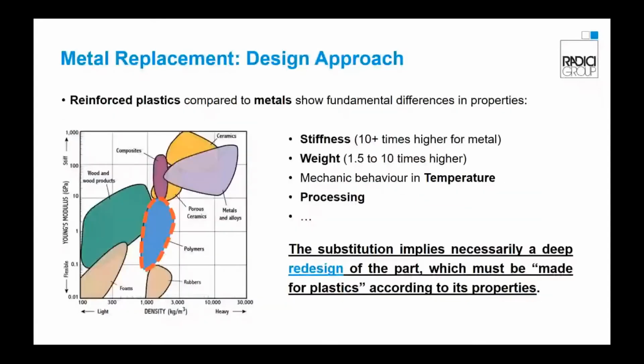As is well known, reinforced plastics, if compared to metals, show fundamental differences in properties. As we can see from the Ashby chart, the stiffness of the plastic is 10 times lower than metals, but at the same time, the density can be 1.5 to 10 times lower. We also have a totally different mechanical behavior in temperature. Indeed, metals have an influence on the property only at a certain level of temperature, generally high. So the substitution implies a deep redesign of the part, which must be made for plastic according to its properties.